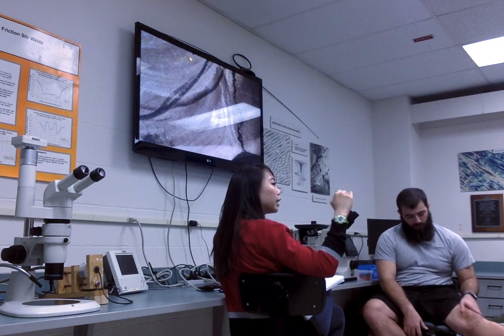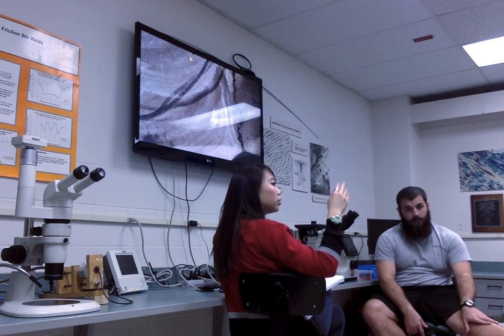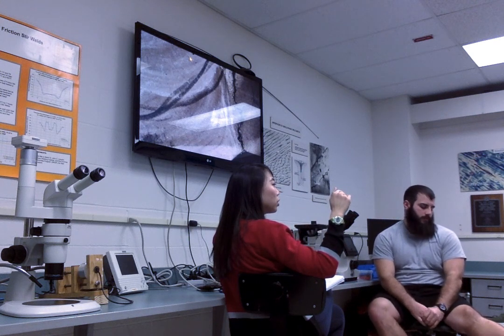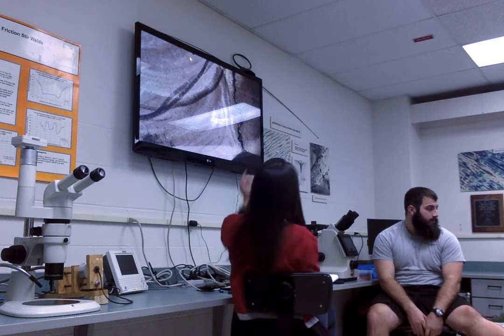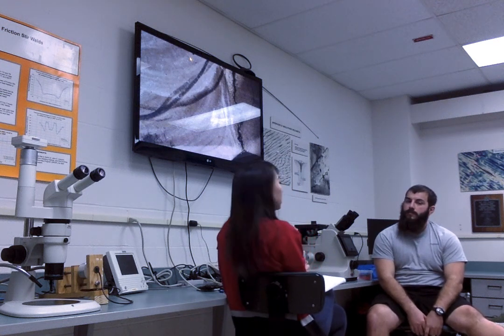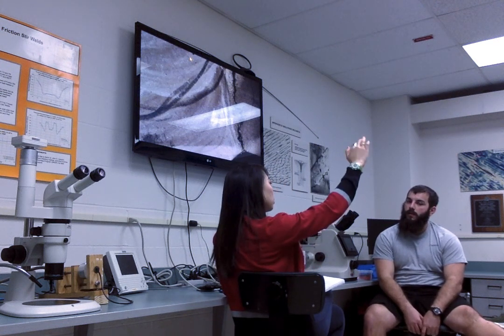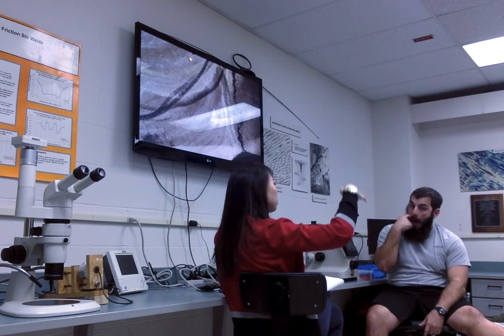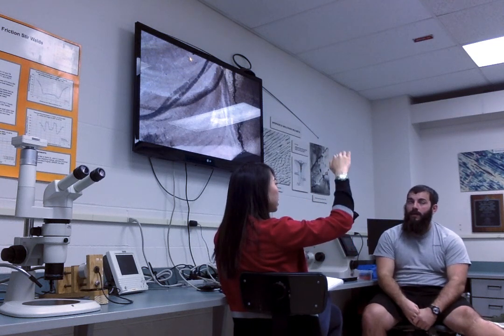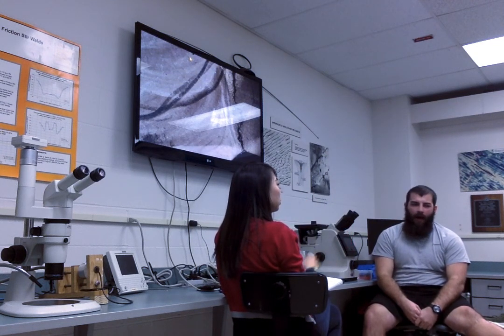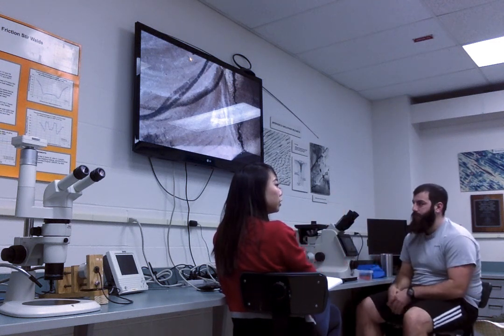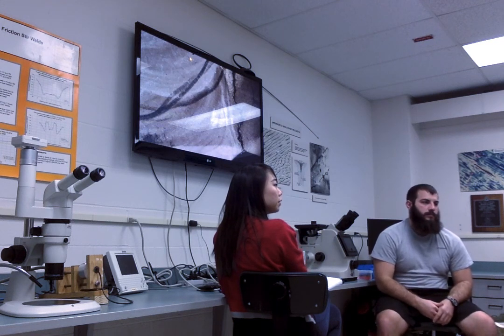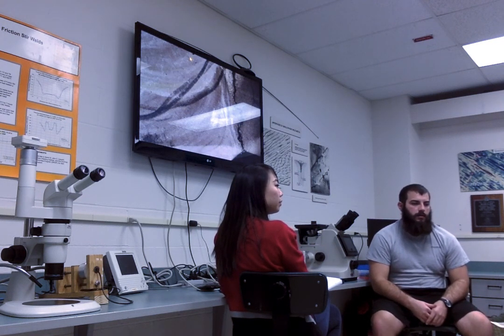And then as you get less strain in your sample or less hydrogen, it's going to be more intergranular. So when the crack starts, it's more likely to start transgranular, or if there's not that much strain, it'll just be intergranular. But as it goes on, it's probably not going to go from intergranular to transgranular. It'll be transgranular to intergranular. Does that make sense? Because when you start cracking, you'll relieve some of the stress that's in your part. Right?